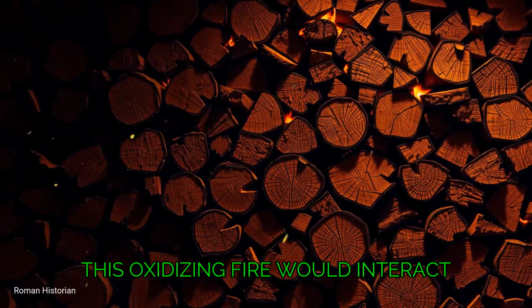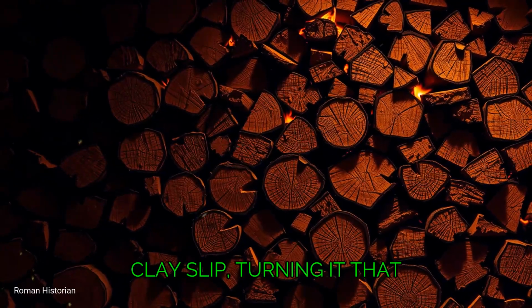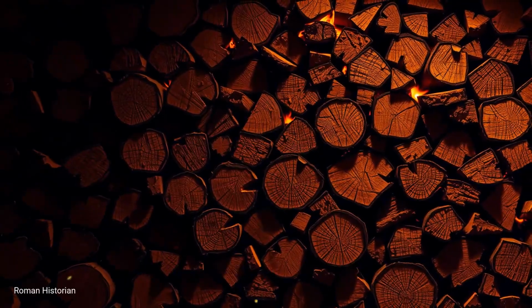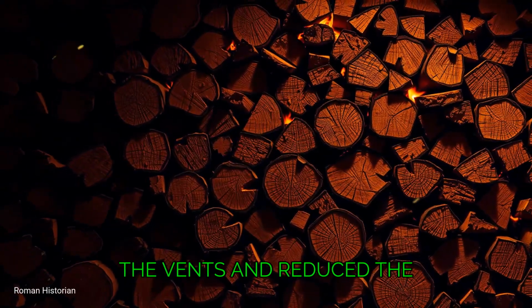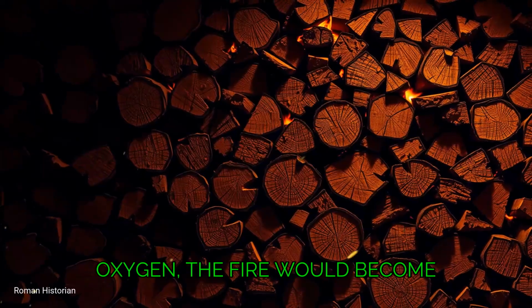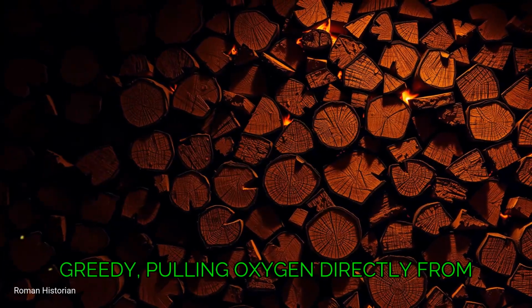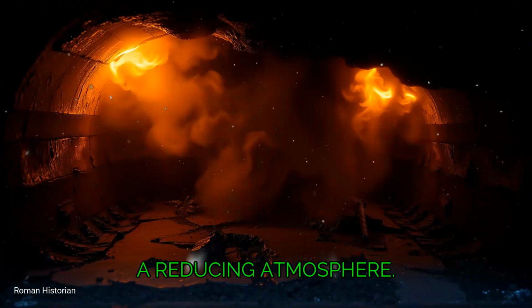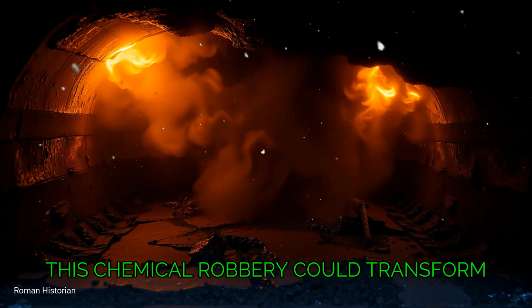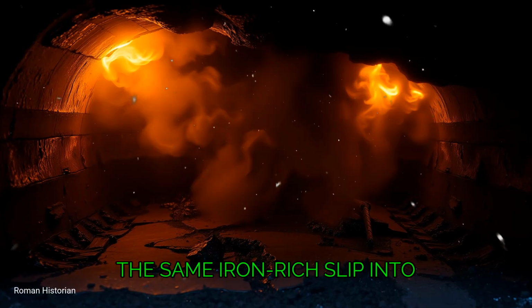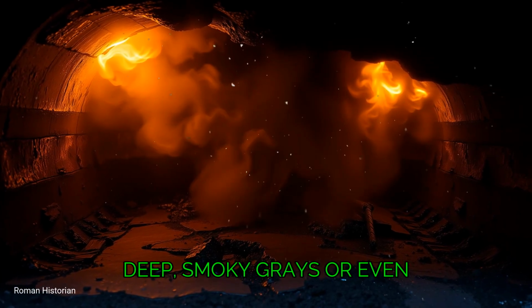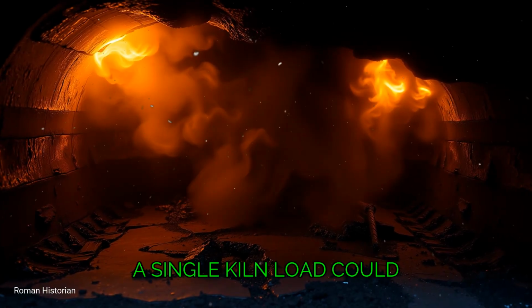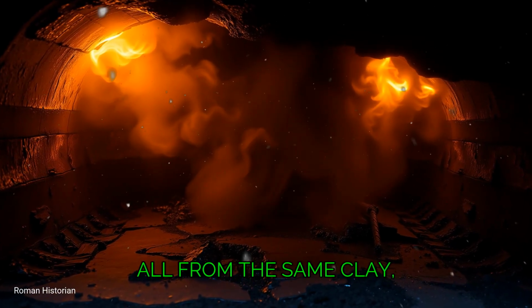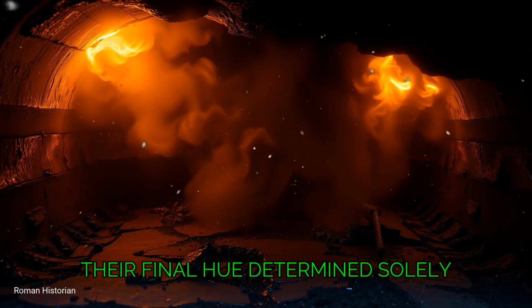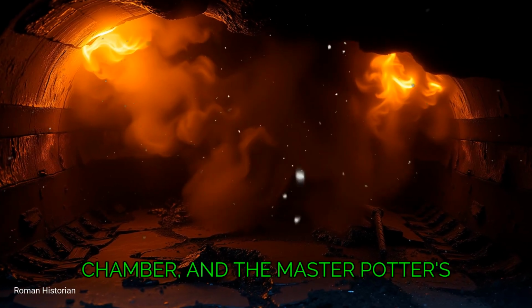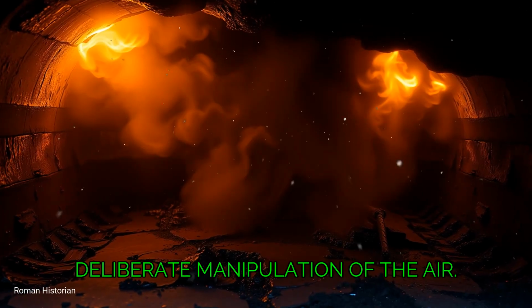This oxidizing fire would interact with the iron in the clay slip, turning it that famous, vibrant orange-red. But if the potter sealed the vents and reduced the oxygen, the fire would become greedy, pulling oxygen directly from the clay minerals themselves in a reducing atmosphere. This chemical robbery could transform the same iron-rich slip into deep, smoky grays or even a blackened surface. A single kiln load could contain pots of multiple colors, all from the same clay, their final hue determined solely by their placement in the chamber and the master potter's deliberate manipulation of the air.